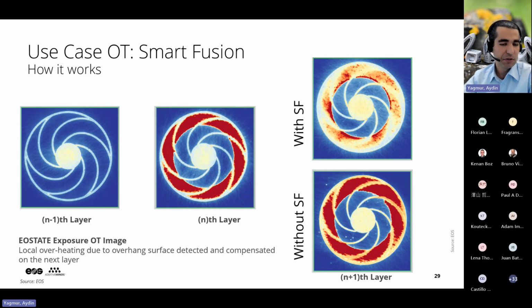If you have ever built parts on an AM machine, you may estimate that in 5 to 10 layers, this overheating will agglomerate into a lot of thermal stresses, and you will see recoater contact and recoater crash. With Smart Fusion, in the next layer, we regulate the energy input of the process so that in these areas, overheating is reduced. And in the coming layers, it will stabilize even more.